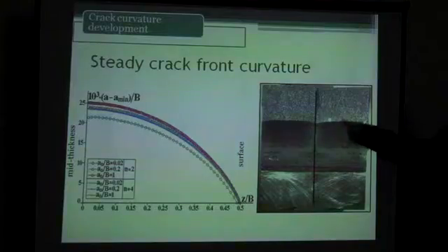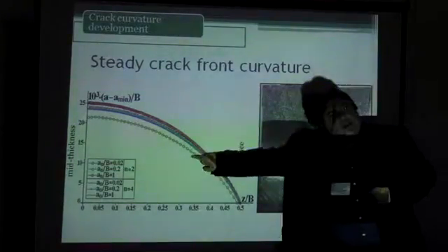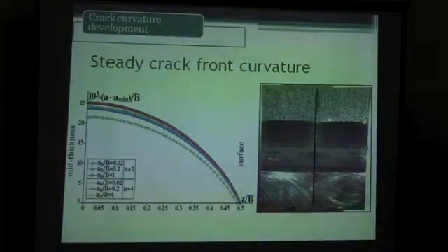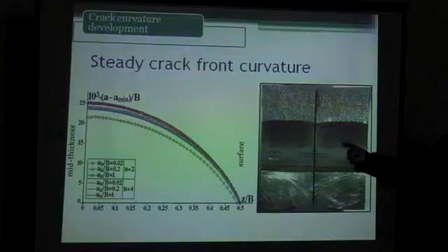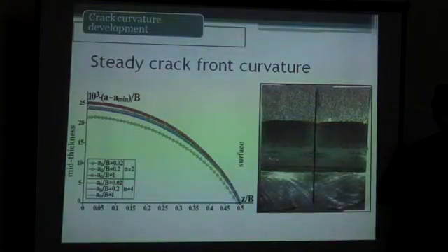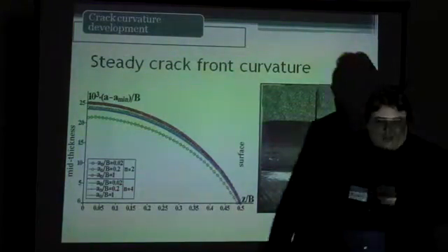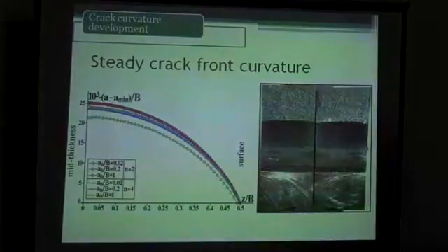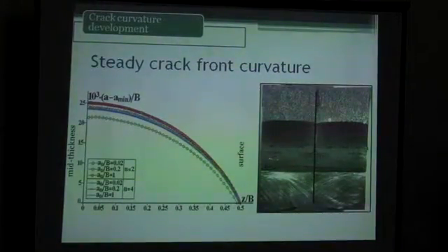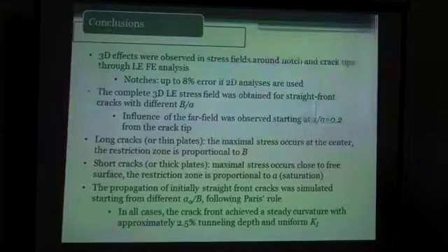So actually this shape was the shape that we predicted only with delta K without considering closure effects, even though this was with a very low R ratio with closure that we measured. So closure is there, but it was not controlling the crack growth, or at least from this inverse problem point of view, the tunneling effect is going to tell us which is the driving force here.